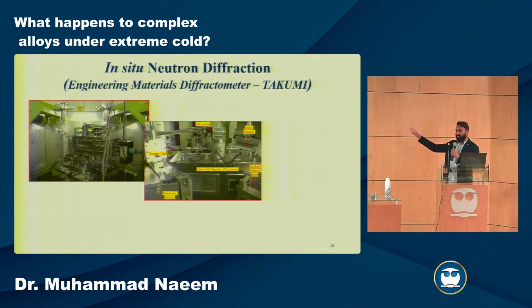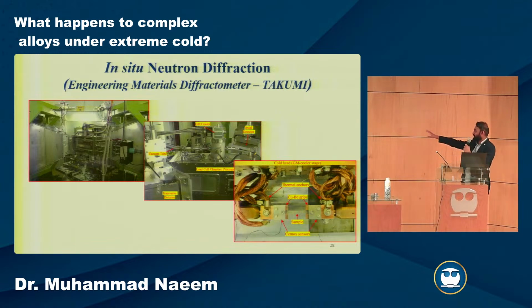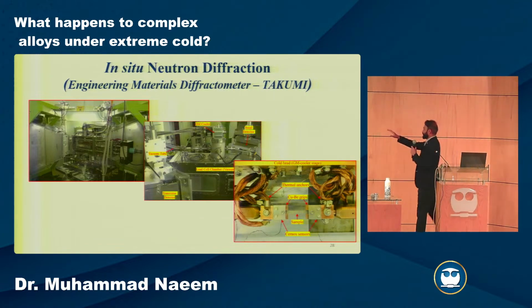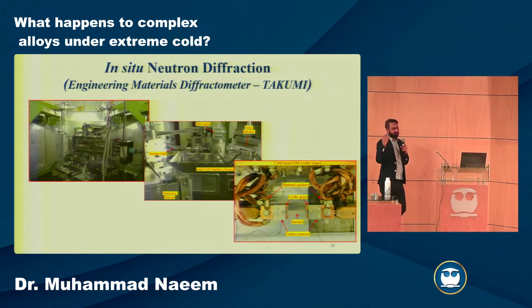This is a close-up of the machine which we use for cryogenic experiments. Here you see these are the detector banks, and this is the neutron beam, and this window is made of vanadium. I mean, steel would interact with the neutrons and you'd get peaks or signals for that, but vanadium is transparent to neutrons. So the beam will just go through that, and then interact with a sample, which I will show over here. So this is a sample inside your machine. Here you see the sample is over here, held with these joints, and these are copper coils which are connected to these grips. Here the temperature is 4.2 Kelvin, which we can achieve with this kind of machine.